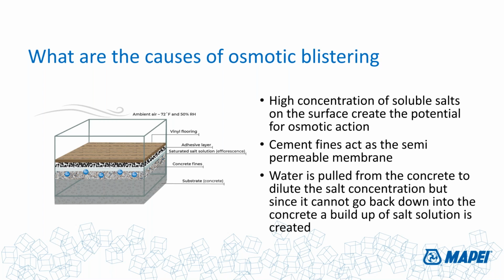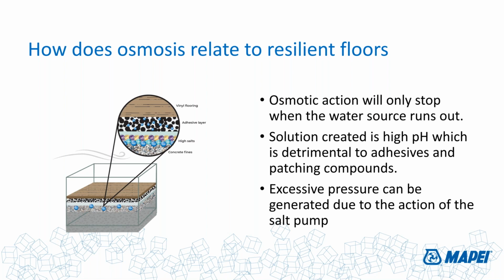Again, the vapor will move back and forth, but the salt solution can't go back down. But since it can't go back down, it still keeps sucking water up. And this is where you get that saturated salt solution coming up and building up underneath your impervious floor covering. This happens under epoxy coatings, this happens after sheet vinyl, LVT, and so on and so forth, where you've stopped the process of evaporation, but osmosis is still going, and you wind up creating this gooey layer of material underneath there.